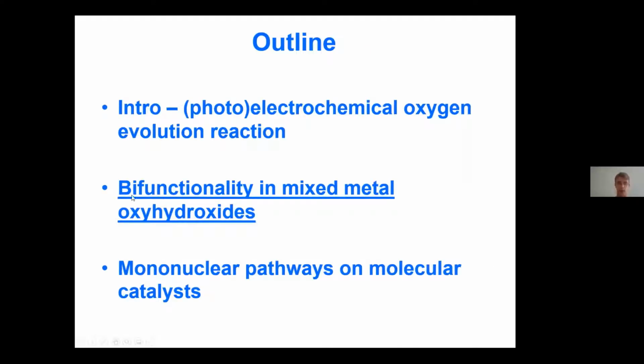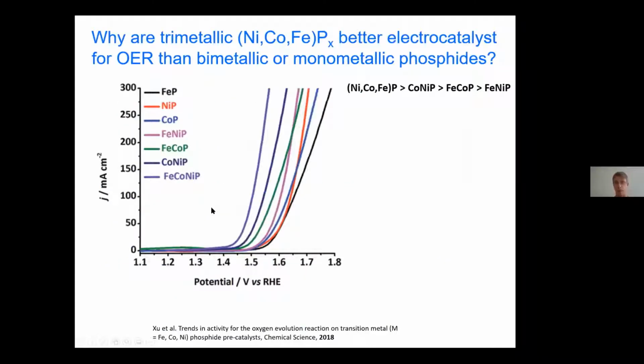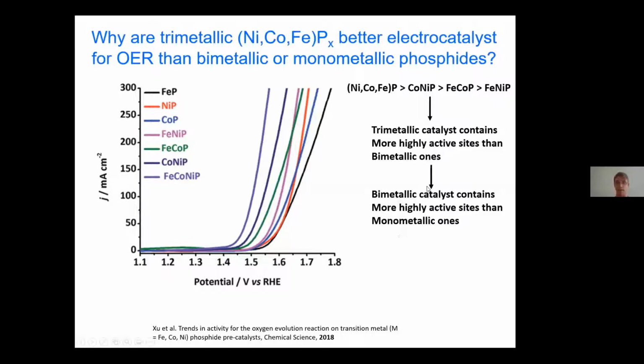So let's go to our first problem, bifunctionality and mixed metal oxyhydroxides. The reason why we started this research was in fact this paper on metal phosphide precatalysts. There it was found that this trimetallic iron, cobalt, nickel phosphide gives a much lower onset potential for the OER process compared to the bimetallic and the monometallic phosphides. So this trimetallic catalyst should contain more active sites that are active at a lower potential versus the reversible hydrogen electrode. And the bimetallic catalyst should contain more active sites compared to the monometallic catalyst.